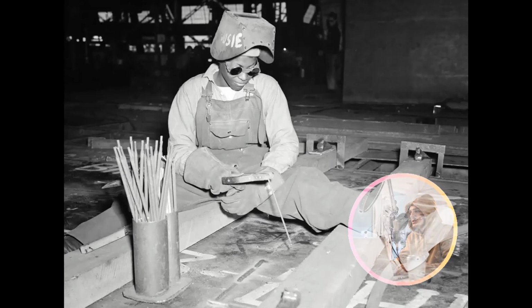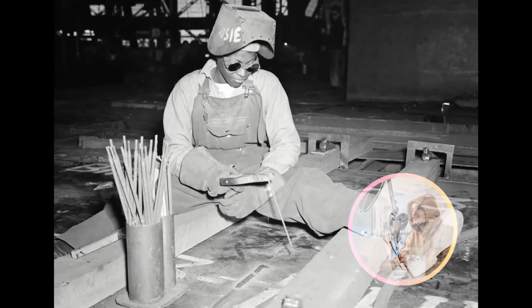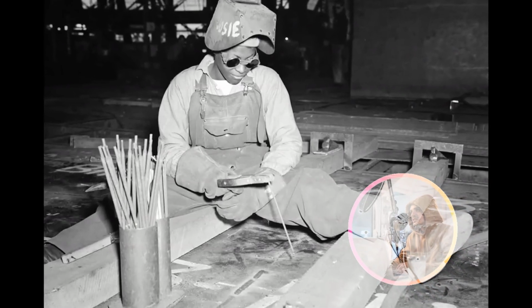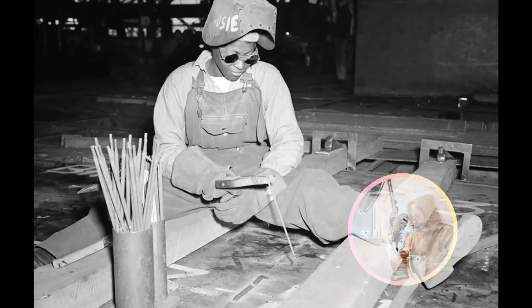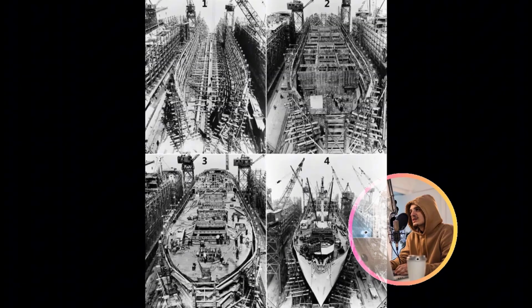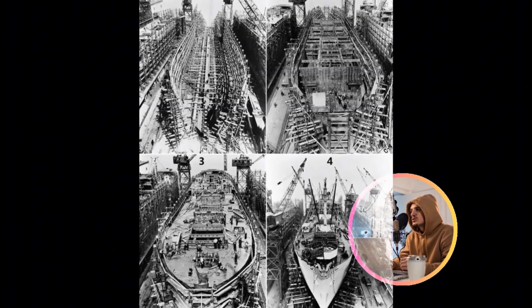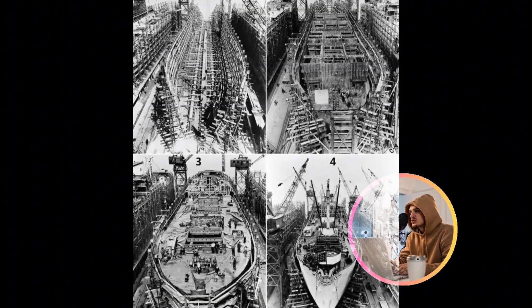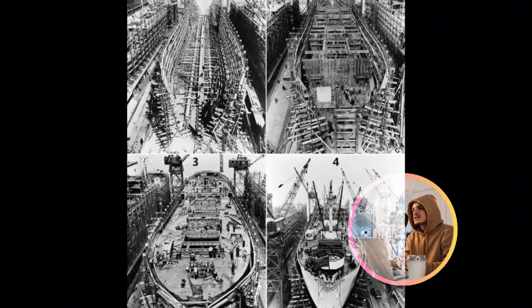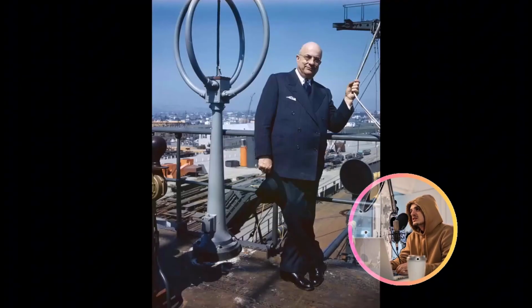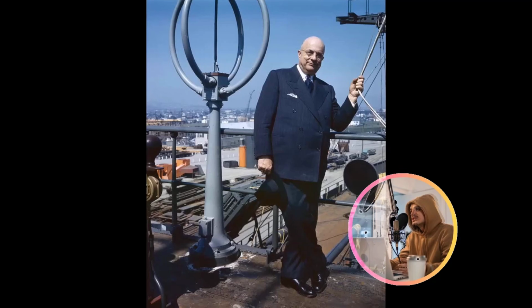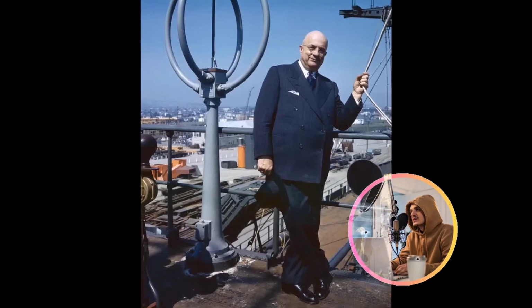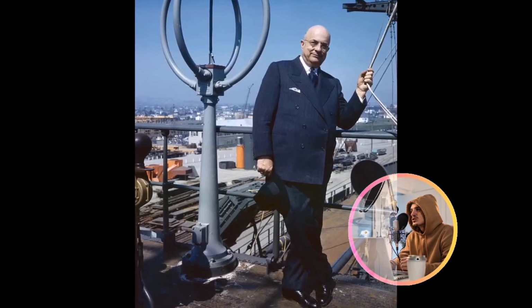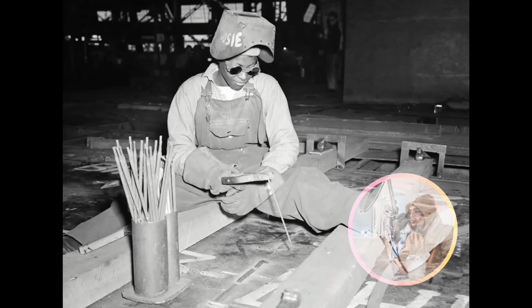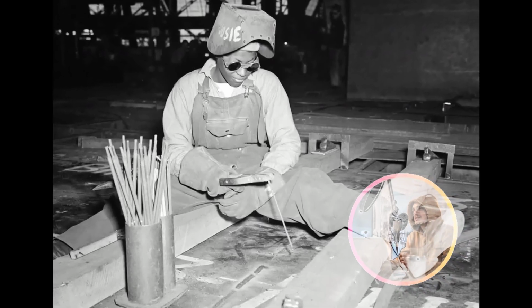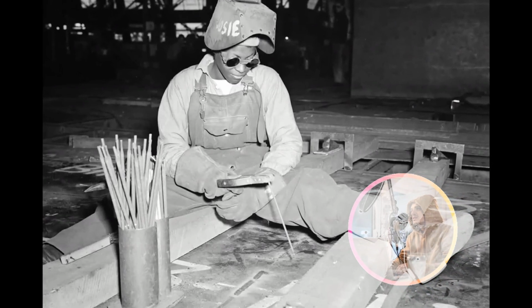Consequently, every single wave that caused the hull to flex sent intense surges of stress spiking directly through these vulnerable corners. When combined with the pre-existing residual welding stress and the steel's increased brittleness at low temperatures, these corners transformed into critical sites for crack initiation, merely awaiting the precise confluence of environmental conditions to precipitate a devastating, catastrophic failure.